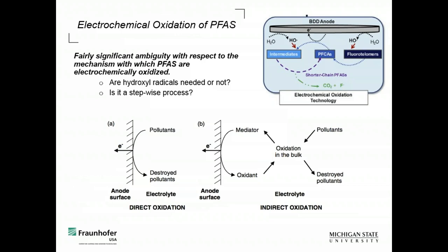There's some ambiguity in the literature as to whether you need hydroxyl radicals or not. Here's one specifically that shows that it's a direct electron transfer process to get it started, and then you need the hydroxyl radical to get an intermediate, and that's how you cause defluorination. Like I said, we've done these experiments with hydroxyl radical scavengers, and we still get good degradation.